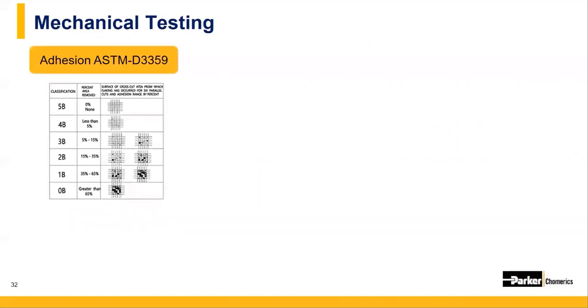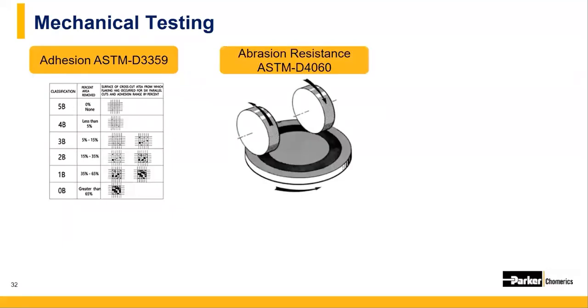Mechanical properties are tested using a whole range of industry standards. For example, adhesion testing, coded for coatings less than 5 mils thick, is done using a cross-hatching tool to perforate the paint layer and then using a pressure-sensitive tape to pull against that cross-cut lattice and determine how effectively the coating will remain on the substrate without flaking or peeling. Abrasion resistance testing uses 2 rolling abrasion wheels on a plated test specimen to determine the number of cycles until a certain coating mass loss or until substrate exposure is achieved.